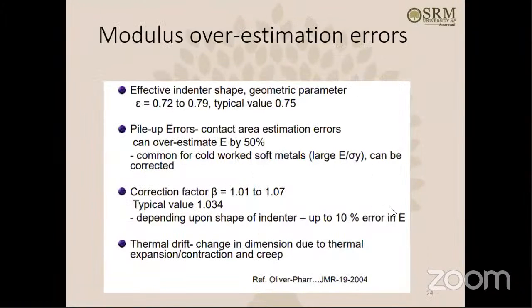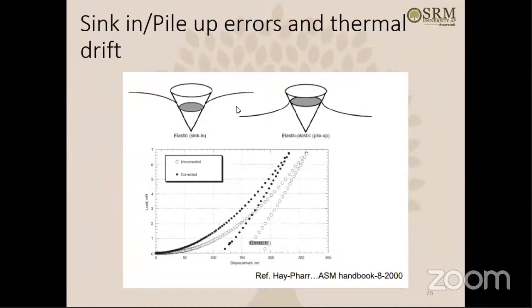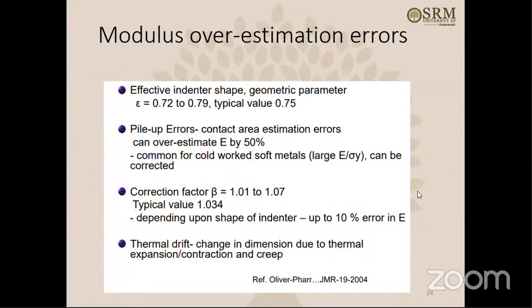Then pile up errors. Pile up errors means, yeah, like this. So as you can see, when you indent the specimen, okay, the conical indenter is coming down like this, and what you see is sometimes the material goes down like this when you indent it, and then when you pull it back, okay, unloading, the material again goes up like this. First the material goes down, then the material goes up. If it goes down, then it's called sinking. If it goes up, then it's called the pile up. Okay. So if that thing is happening, then it shows a lot of errors.